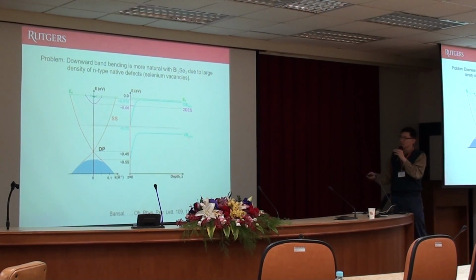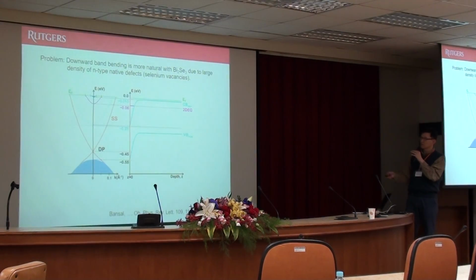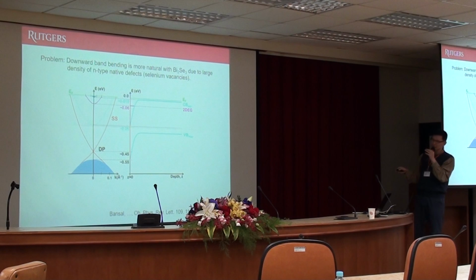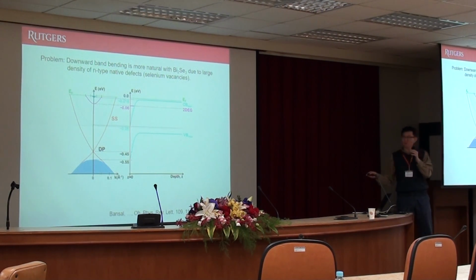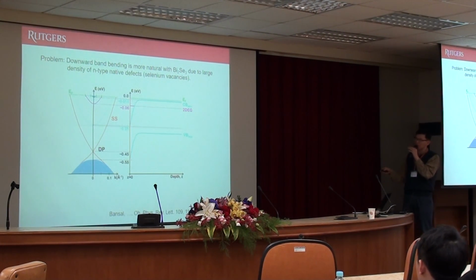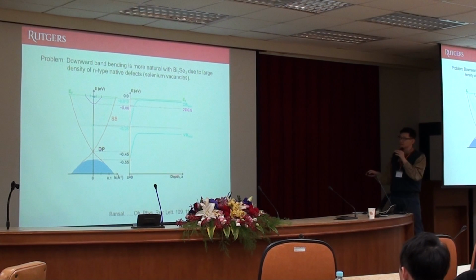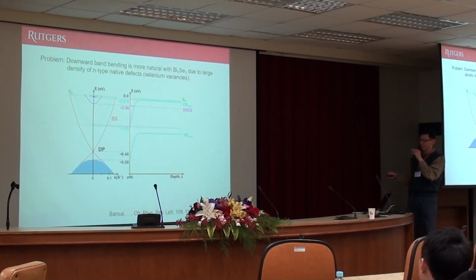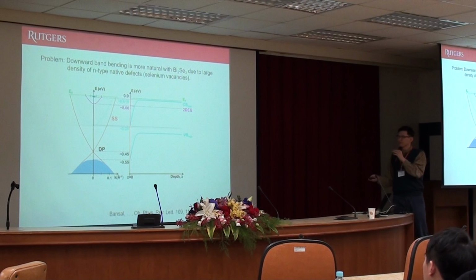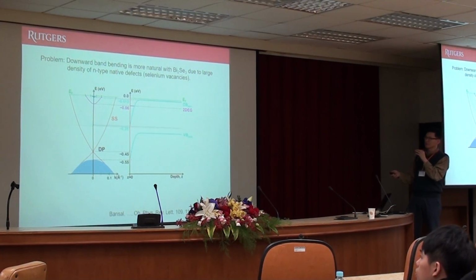But the problem is, all the bismuth selenide materials, we know that it turns out that they have this downward band bending. So this is downward band bending. Conceptually, if you achieve upward band bending, then you can make the sample insulating. But it turns out that whenever you make bismuth selenide, you always have downward band bending. So again, there's a problem here.